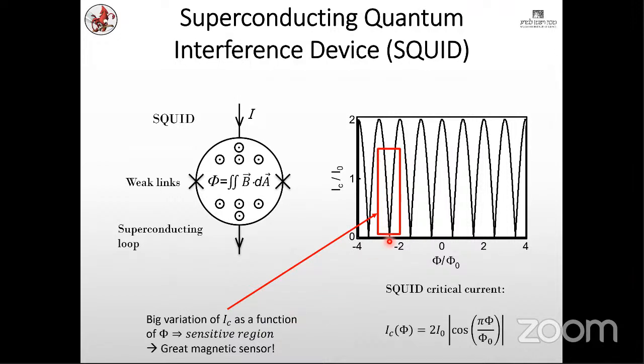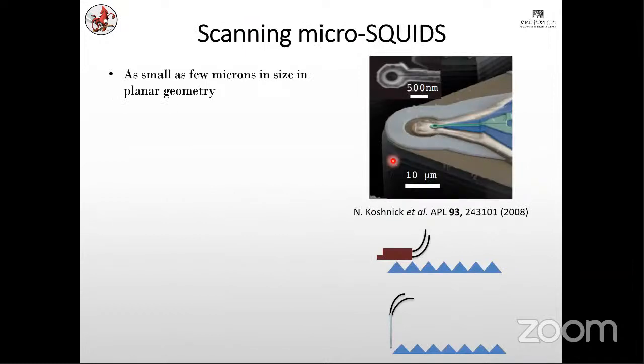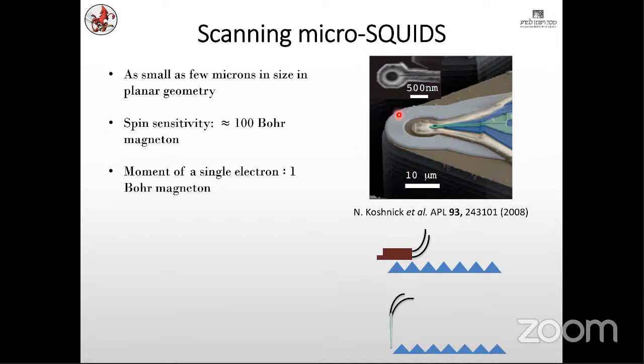So as you see in such regions, the critical current changes quite sharply with the magnetic flux. So that's the property that's used to sense magnetic fields using a SQUID. And these SQUIDs can actually be made quite small. So here is a SQUID which is about 10 microns or even smaller. So it is done using planar lithography techniques. And the spin sensitivity can be as small as 100 Bohr magneton in these planar devices. These can also be used to scan. And it is about 100 times larger than the typical moment of a single electron, but still quite sensitive.